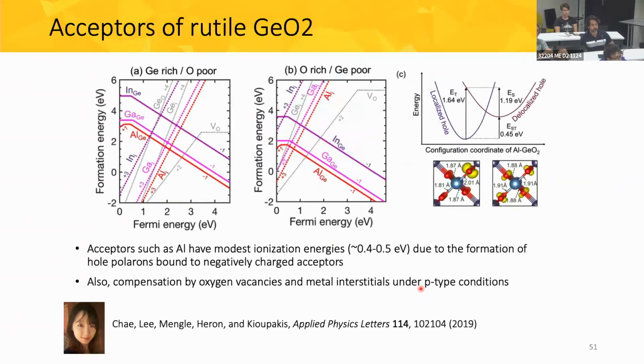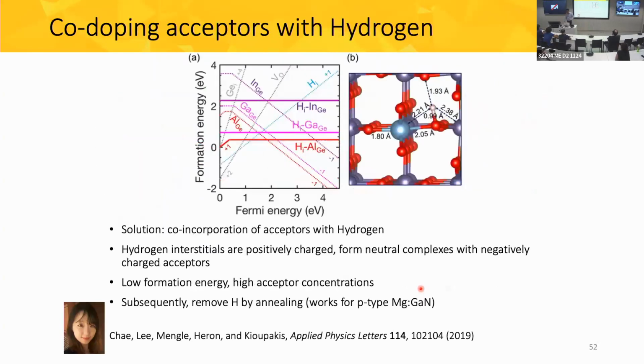Great question. Indeed, we do see here also that we have a very high ionization energy that we predict. Again, there's some uncertainty in these numbers on the order of 0.1, 0.2 eV. So experimentally, we're still not sure what the exact numbers will be. But yes, we do expect poor ionization here also. That's indeed the case. However, we hope that we're able to overcome this by incorporating very high concentrations. If you see here, the formation energy of this complex is very low, right? It's like a quarter of an eV or less. So what we expect to see is that when you go to very high synthesis temperatures, we'll be able to incorporate a very high concentration of aluminum and perhaps get conduction through an impurity band of this material.